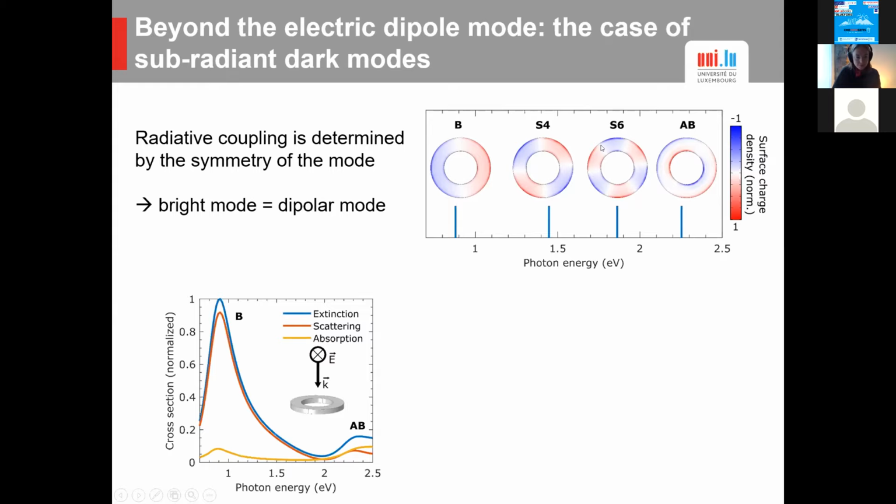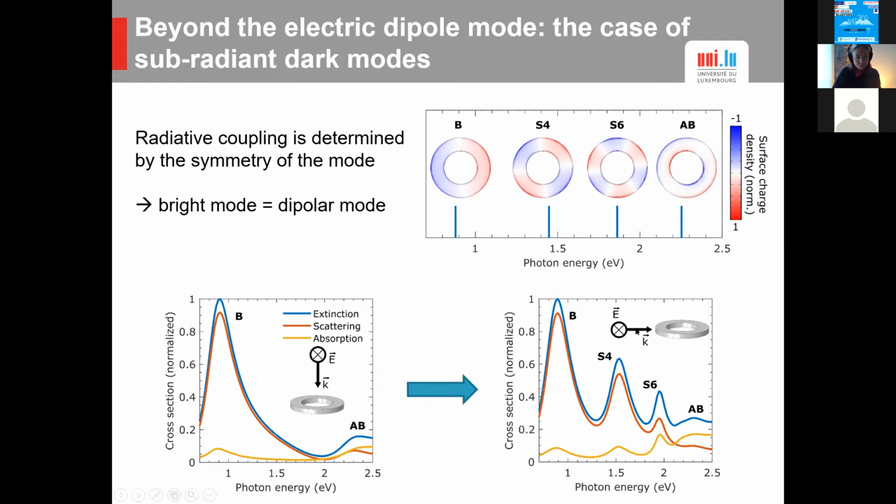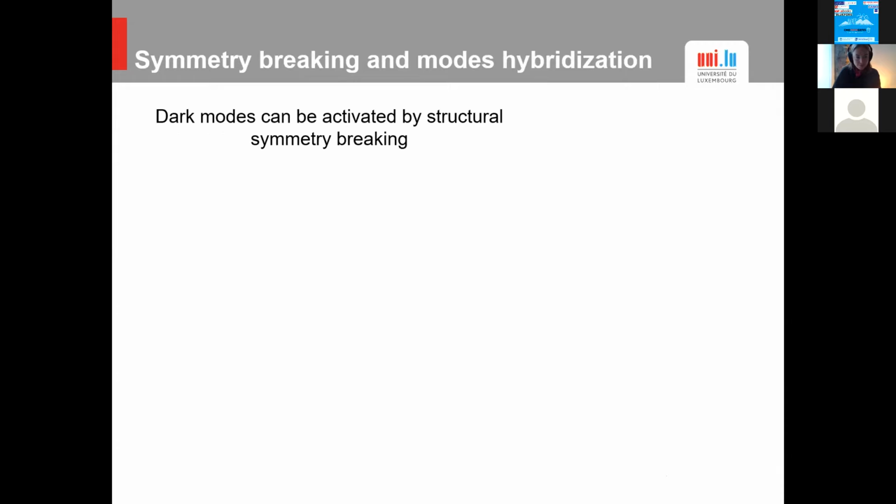And as you can see, if you shine linearly polarized light on a ring, you can excite just the bonding and antibonding modes that are actually the so-called bright modes. You don't have signature of these dark modes. Of course, if you consider an unrealistic polarization and experimental condition, so you break the symmetry somewhat locally in the near field, you can also excite these dark plasmons, these subradiant modes, but this is unrealistic. So the way to actually activate these dark modes is to break the geometrical symmetry of the system, for instance,